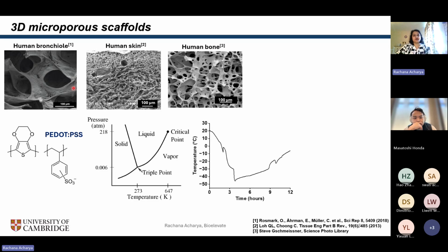So we can use the triple point of water to actually create this structure. Here I'm showing you the triple point of water phase diagram, and on the right, I have a temperature profile of my fabrication process. We fabricate these platforms using a process called freeze drying or lyophilization. And on the left, I have temperature as a function of time. So we start in the liquid phase, PEDOT:PSS, the polymer in its aqueous dispersion.